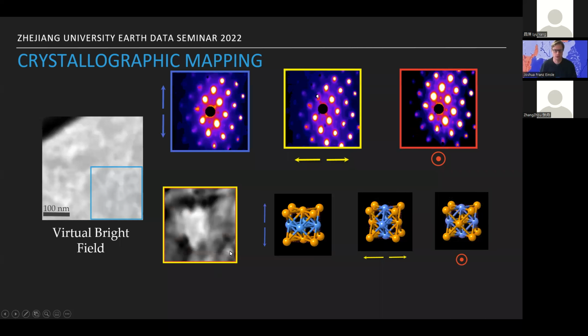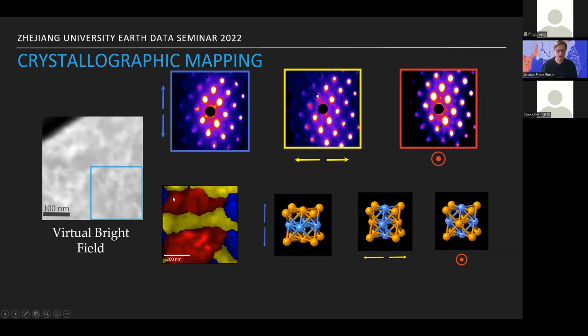This is looking down the 100 axis. What we're able to do then is get a good estimate for the number of grains in a particular orientation. And this confirmed one of our initial assumptions, which is that all the tetrataenite orientation directions are going to be present in the sample. That was a nice result, but it didn't tell us anything about the matrix.